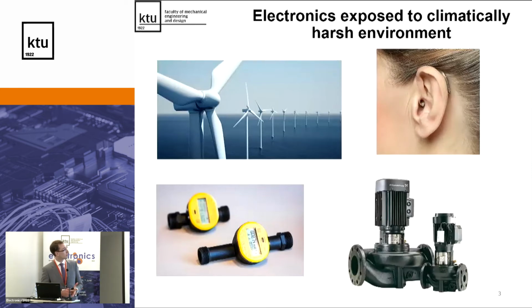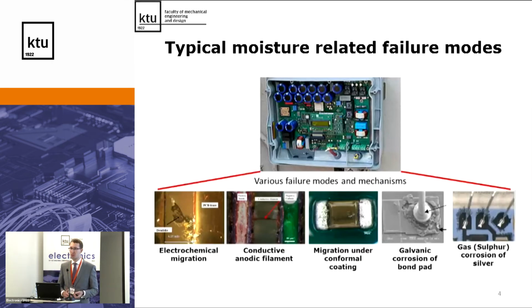So why is it important? We have many electronics used outside and exposed to harsh environments, like wind turbines and hearing aids. Also, people are sweating, and it's a salt and harsh environment. And then we have water meters, water pumps. Exposure to the harsh environment leads to a number of failures: electrochemical migration, conductive anodic filament, migration under conformal coating, galvanic corrosion of bond pad, and gas corrosion of silver. We also have alteration of material properties. Then we can also get short or open circuit.